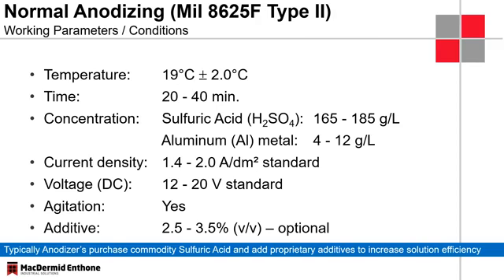We use some proprietary additives for the anodizing bath, and these additives are really designed to stop the redissolution. They act a little bit like inhibitors on the surface. They protect the anodized surface, and it will reduce the dissolution rate. And a lot of people will actually see that as an increased efficiency or an increased thickness after the same plating time. So that's where this all comes from.